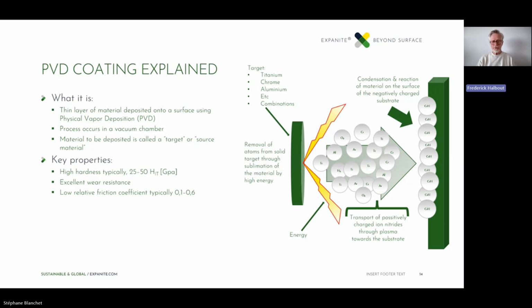A commonly used PVD coating is a combination of aluminum and chromium nitrides, and that is actually the case for the one that Ramén is using, which brings a hardness level up to 5,000 Vickers. The thickness of a coating is no more than 3 microns, plus minus. You can make them thicker, but not much. So if you go to the next slide.